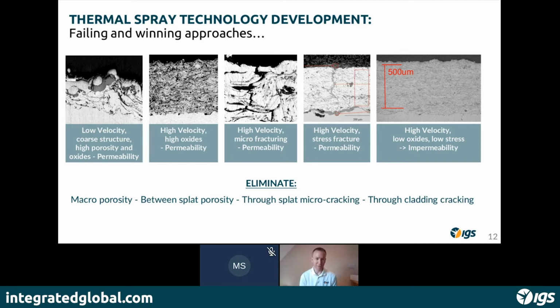We're an on-site thermal spray company. That's our business. And these material developments have come at some cost to IGS because we've experienced the failures of these systems when they're not designed and they're not applied correctly. So we've used low velocity, we've used standard off-the-shelf conventional alloys, we've used micro-cracking materials, which are very good for high erosion environments or abrasion environments. You can have a very hard material that micro-cracks, but then provides a very good sacrificial barrier to erosion. But if you're looking at corrosion, those microcracks then provide a pathway to the substrate.